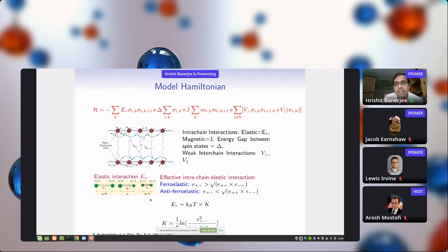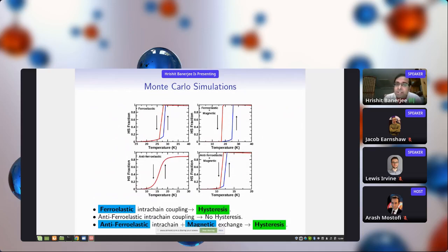So with this model in mind, let us move to the Monte Carlo simulations that we did to determine, in a parameter regime, not taking any first principles assumption yet, what is the basic interplay between the ferroelastic and the magnetic, and the antiferroelastic and the magnetic situations. So in the case of a ferroelastic interaction, we plot the high spin fraction versus the temperature on a lattice model, and we find that there is already a hysteresis, and the magnetic interaction only enhances the hysteresis width in this case. However, for the antiferroelastic intrachain interaction, we find that there is absolutely no hysteresis, but this is still almost a first order kind of transition, going towards first order.